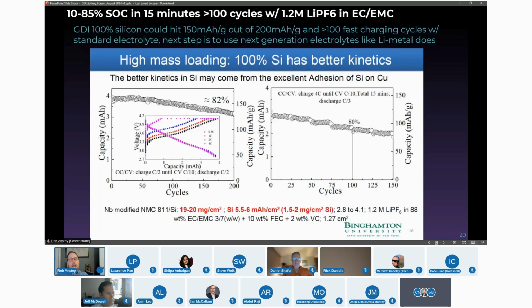Now that's compared to GDI. GDI was able to do this over 200 times back to back at 4C in third-party testing by Professor Whittingham's group. And this was able to show you that we could actually fast charge repeatably. And his conclusion was, look, they're getting a lot more energy out of the cathode than both lithium metal and graphite at a much higher energy density. Once again, 10 to 80% of what? 10 to 80% of what watt-hour per kilogram, what watt-hour per liter. So this is a high energy density, and you're getting a ton of it in 15 minutes.